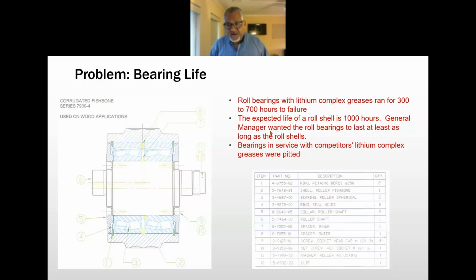The problem is that their roll bearings, with the lithium complex grease that was recommended by CPM, only lasted 300 to 700 hours before failure. The expected life in this failure is due to many factors, but one big factor is load. The load comes from the hardness of the wood, the moisture of the wood, and the throughput of the pellets through the pellet mill. The expected life of the roll shell is about 1,000 hours. So the general manager wanted the bearings to last at least as long as the roll shell. That was our goal, to reach 1,000 hours for bearing life.